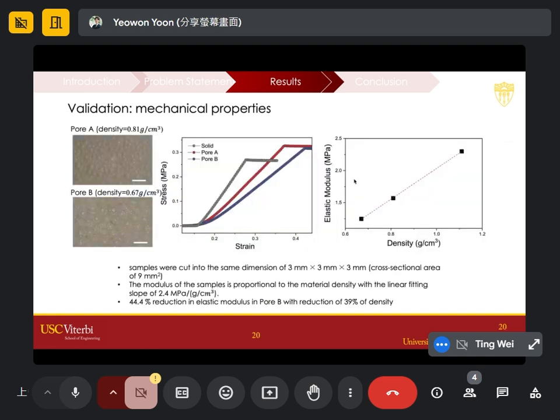So here we have pore A, pore B, using different density. And then this is a mechanical compression test to calculate the elastic modulus of each material. Whenever the density is full, where there's no bubble, and then it reduces to about 0.67 grams per centimeter cubed, we were able to decrease the elastic modulus by 44%, where the density is down by about 40%.